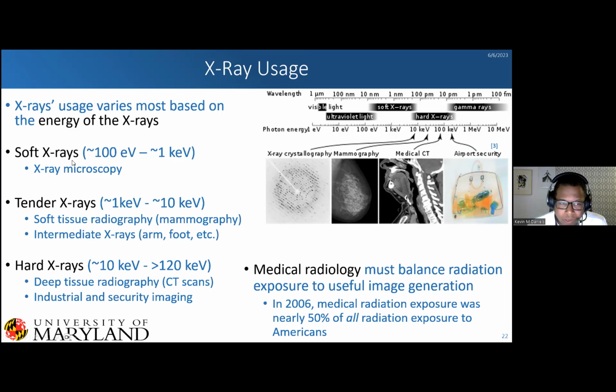And so we're really interested in this soft X-ray to tender X-ray range, so around 100 electron volts to around 10 kiloelectron volts, at least for now. And really, again, it goes into this medical radiology where you want to balance radiation dose with useful image generation. In 2006, for instance, about 50% of all radiation was attributed to medical irradiation.